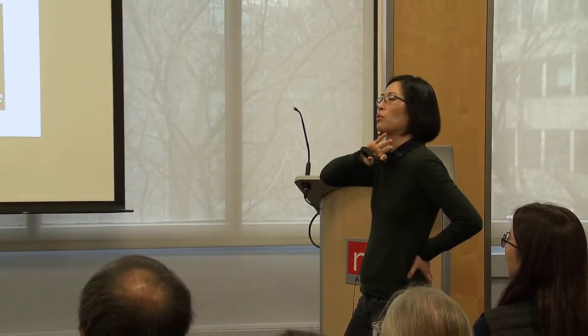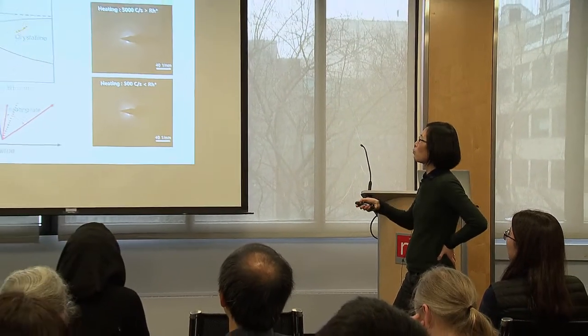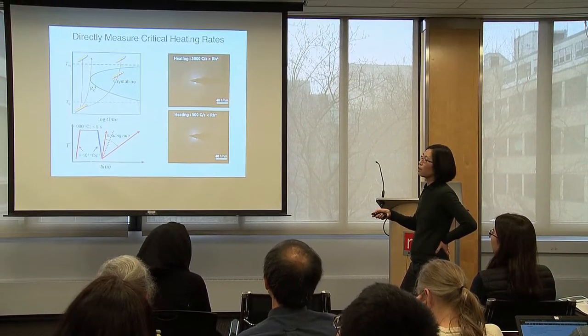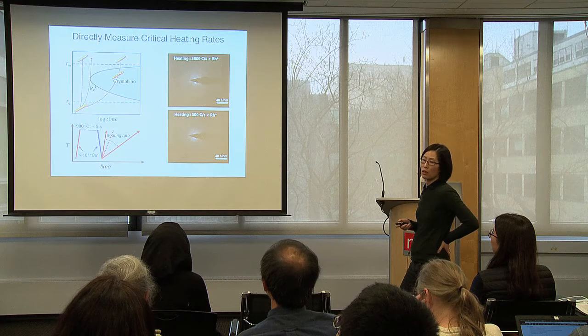This is experiments. We actually recycle our rods. So the way we recycle them is that we go to 900 degrees Celsius for less than 5 seconds to melt everything. And then we quench it as fast as we can. And then now we vary the heating rates.